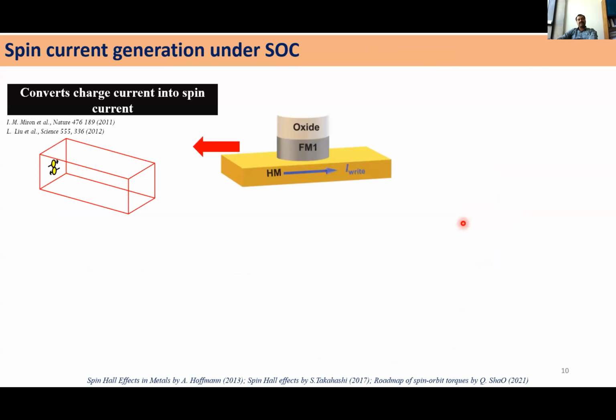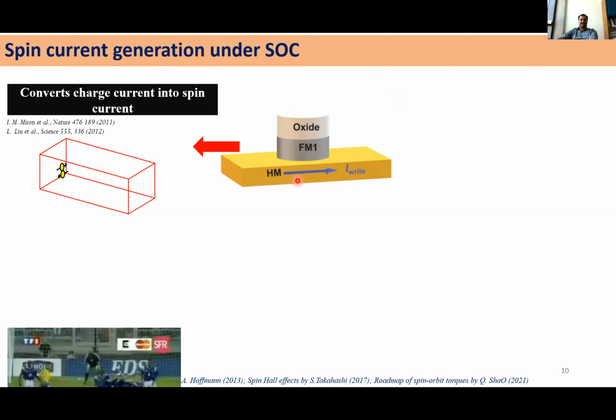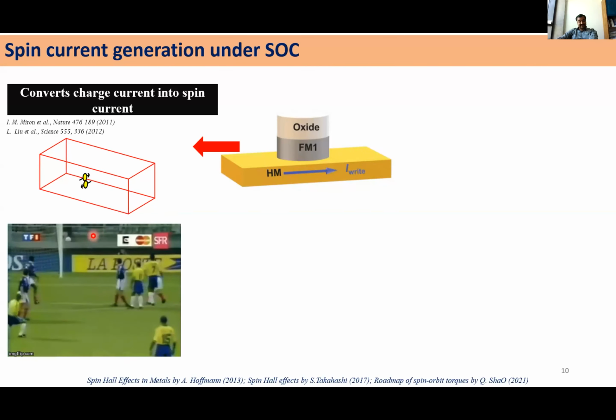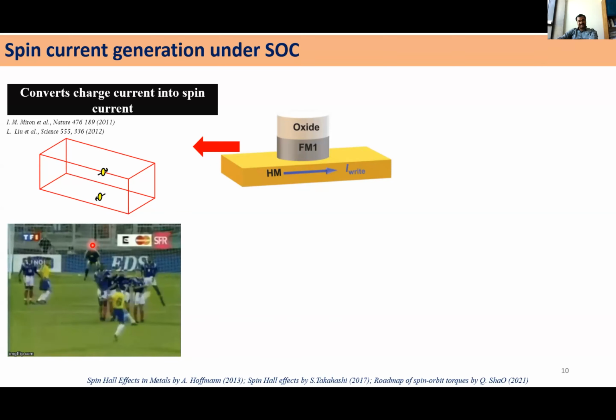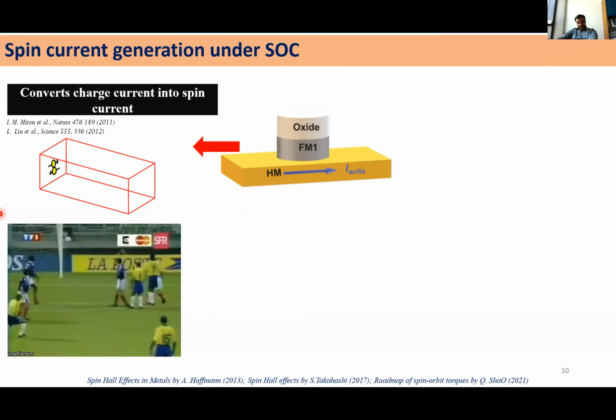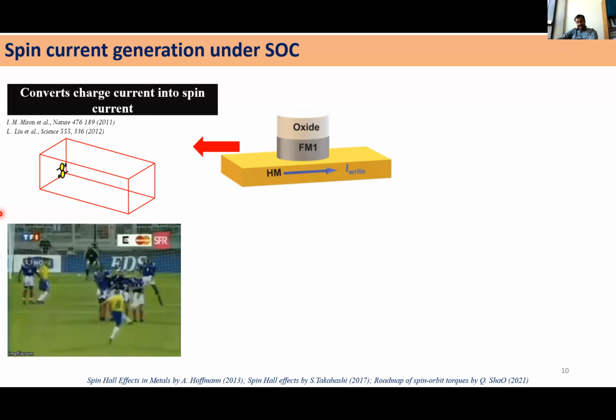So the solution is to look beyond STT, and spin orbit coupling helps us in that. You already understood that by applying a charge current through a heavy metal, we can generate a spin current that can switch the magnetization of the ferromagnetic layer. So you can do the reading as usual like STT-RAM in a magnetic tunnel junction, but writing can be done through an in-plane charge current that is converted into a transverse spin current that helps us in switching. It is just like this penalty kick, where by applying some spin, the ball can go to the net, right?